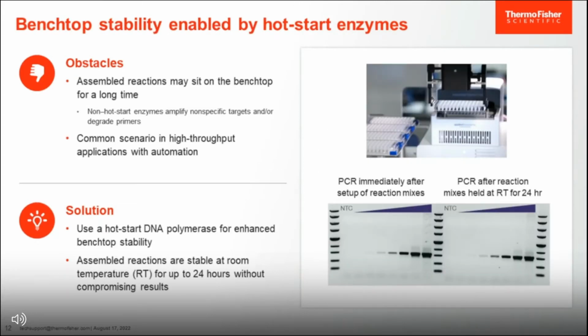Now, if you set up PCR using liquid handling or robotic platforms, stability of assembled reactions at room temperature is critical to achieve optimal results. Hot start modifications of PCR enzymes make this benchtop stability possible, and if you use a stringent hot start, you can achieve stability for up to 24 hours. As you can see in the gel image on the right, the same result was obtained when PCR was run after the setup and when it was left for 24 hours at room temperature.